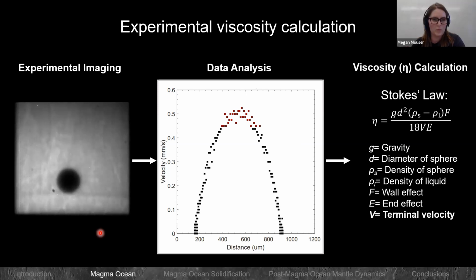We know the frame rate of the camera, and we know the dimensions of the capsule. So what we can do is measure the position of the sphere as it's falling, and plot it up into a velocity profile. So we have distance versus velocity. What we're interested in is the peak of this curve, which is the inferred terminal velocity of this experiment. We take an average value of this terminal velocity, and we can plug it into Stokes' law.